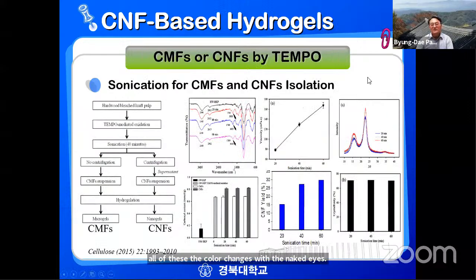Okay, so up to now, I talked mainly about the CNF or CNC-based composite materials which are able to detect color changes depending on the pHs. Now I'm going to change to the hydrogels, the nanocellulose-based hydrogels. So first, what we did is TEMPO oxidation of bleached kraft pulp fibers, and then we did sonications at different times, 40 minutes or different times, and then we separate the top part. The supernatant becomes cellulose nanofibril. The bottom part is cellulose microfibrils.